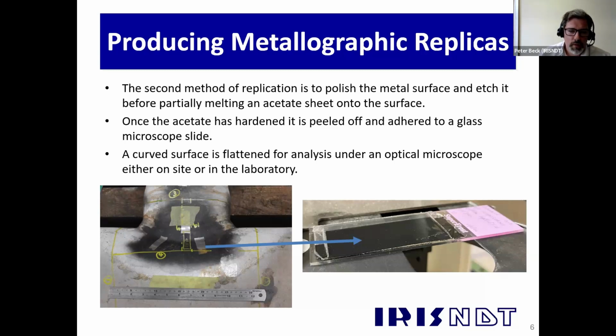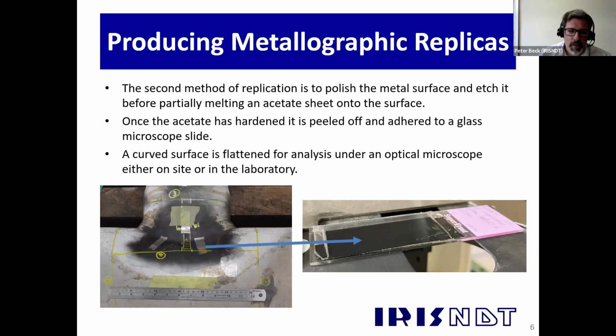The main advantage with this method for us is that once you peel the replica off, once the paint's dry and everything, you can adhere this to a glass slide and flatten it with the back of another slide. Once this is flattened, that allows you to then put it under an optical microscope. So we're taking something that is a curved or undulating surface and making it flat for assessment. That's the real key reason we would use this method. The PU method would also give us the same resolution, but not the flat surface, so it would be very difficult to focus and assess a replica from that method.